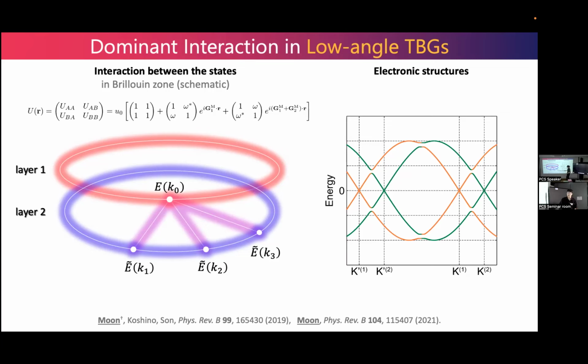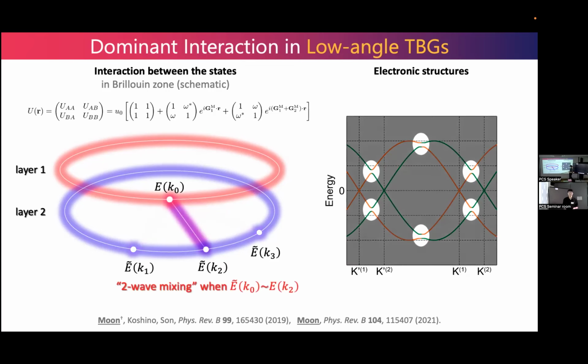So usually at most wave vectors, these states have completely different energies from these 3 states. That is the reason why at most wave vectors, the electronic structure of twisted bilayer graphene is just a decoupled structure. At a specific wave vector, however, one of the states becomes degenerate with the layer 1 state. At that point, band opening and van Hove singularity appear. That is the interaction in low-angle twisted bilayer graphene.